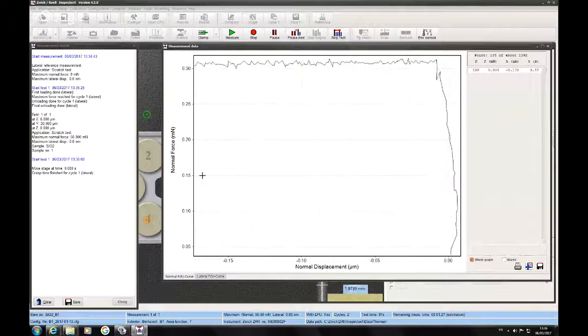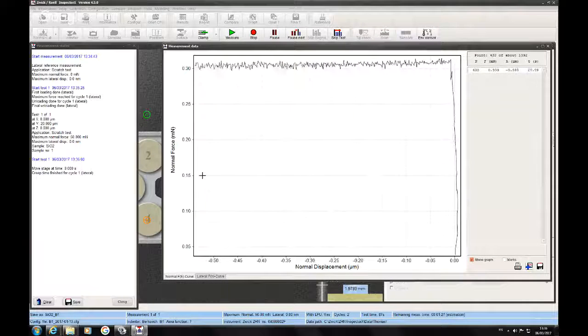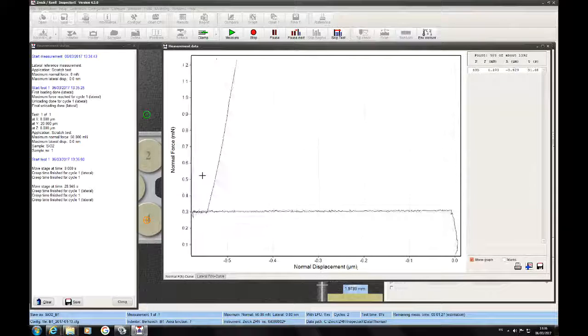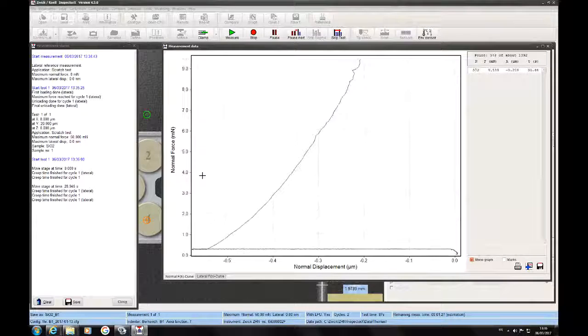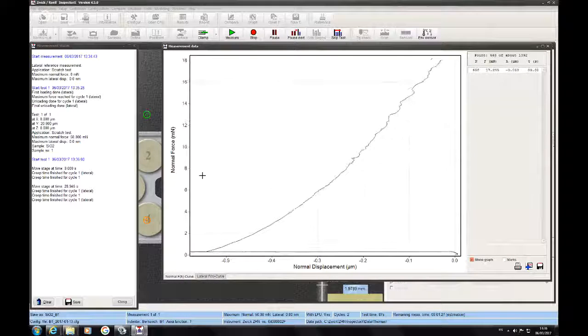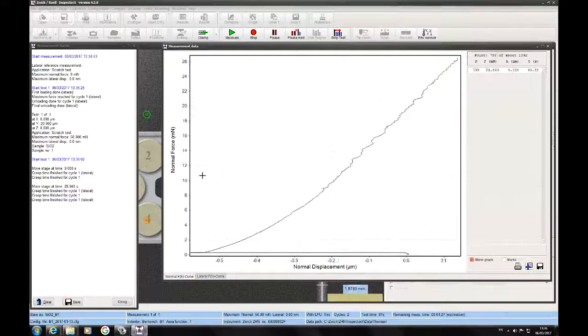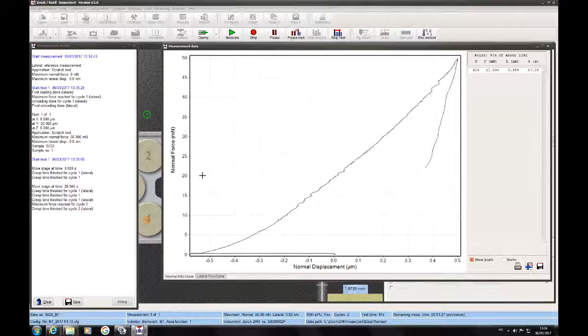And this is the pre-scan of the surface to measure slope and roughness. After that, the scratch will start at the end of the scan range, going back to the start position. So the maximum force will be applied at the starting point. And we have an additional scan length outside the scratch of about 20 micron defined on both sides. So you see on the fluctuation of the curve already that there's some fracture in the coating. 50 millinewton was the maximum. Of course, we can also program a scratch with constant force. So now after unloading, again a scan is done. It's called post-scan, to see the remaining plastic deformation after the scratch.